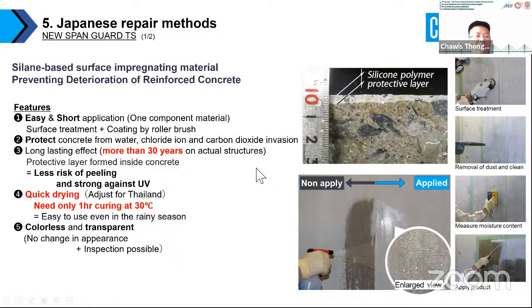The special feature of this product is that it is easy to use, with only liquid material, and can be applied with a roller after surface treatment. The water repellent layer is able to protect against the entry of deteriorating factors such as water, chloride ions, as well as carbon dioxide. It has a long-lasting effect; our records show more than 30 years on actual structures after applying the product without repainting. So there is a low risk of any deterioration such as cracking and spalling.